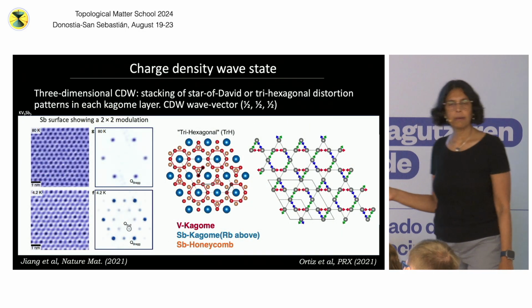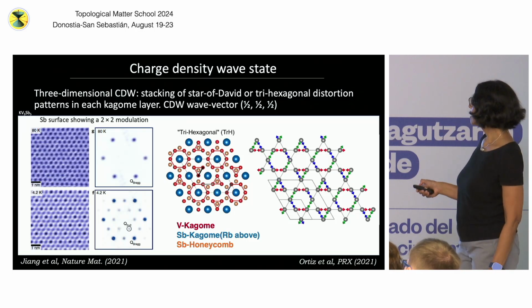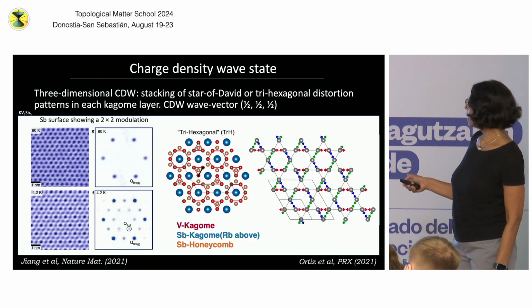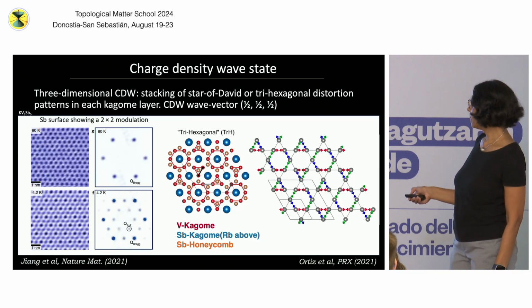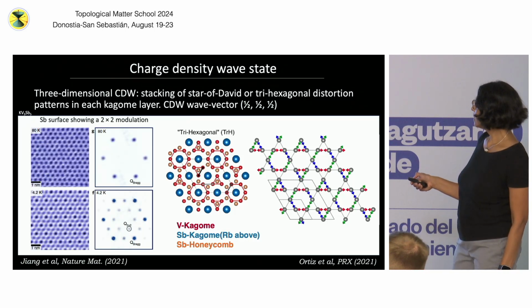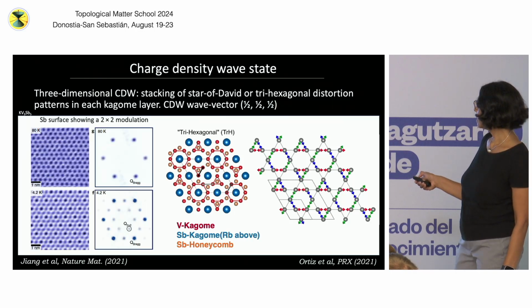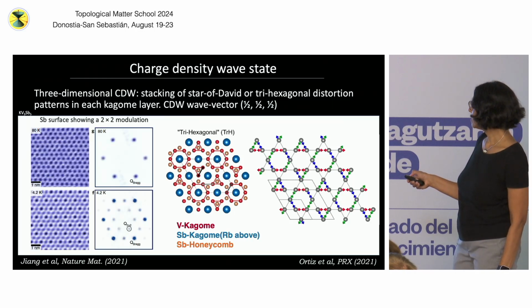So let me show you the CDW first. This is an image above the charge density wave transition. It's from this paper. And you can see the Bragg peaks. It looks like a hexagon, because it's the antimony surface.